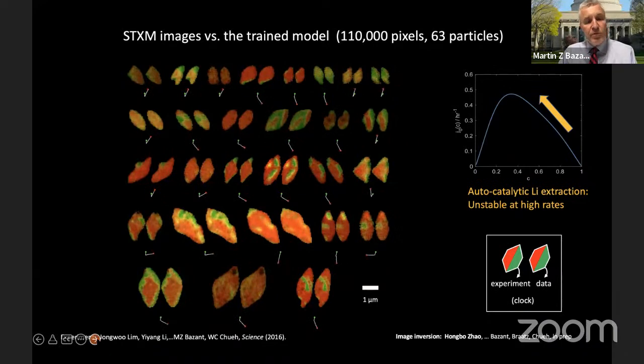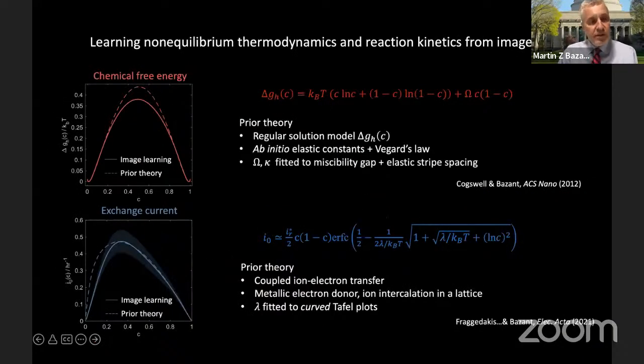So now if we put all this together, what do we learn? Well, in the top here, we see the red curve is the learned free energy function. And I believe this is the first, maybe ever, experimental measurement, if you want to think of it that way, of a non-equilibrium free energy landscape. It's impossible to study in an equilibrium experiment. If I create a system which is at the peak of this energy, it immediately drops to the minima and phase separates. So you can't really hold the system there. But because the movies of the images here follow the system out of equilibrium, being driven over the barrier and back down, essentially we can map out the free energy surface. So I think that's pretty interesting.